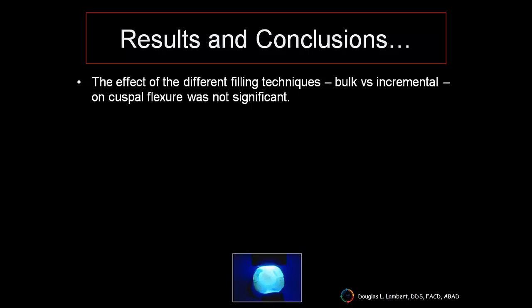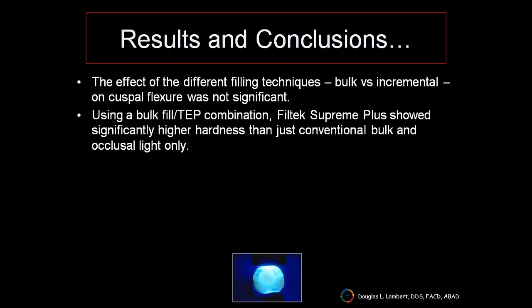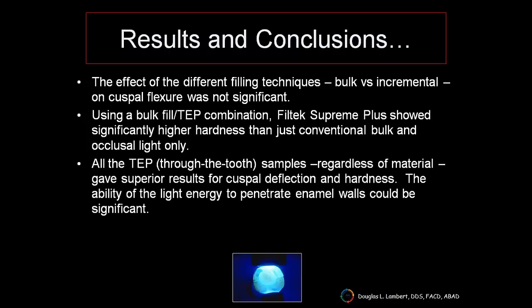Here are some of them. The effect of the different filling techniques, bulk versus incremental, on cuspal flexure was not significant. Using a bulk fill and through-the-tooth curing, trans-enamel polymerization, the Filtek Supreme Plus showed significantly higher hardness numbers than conventional bulk fill with occlusal light only. In other words, the properties of the Filtek Supreme Plus improved when the light was shone through the tooth rather than just from the occlusal. And all the through-the-tooth trans-enamel polymerization samples, regardless of the material, gave superior results for cuspal deflection and hardness. The ability of the light energy to penetrate the enamel walls could be significant.